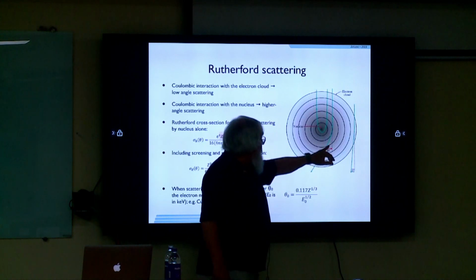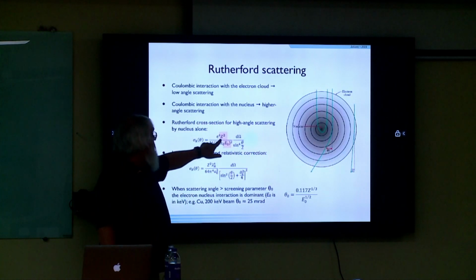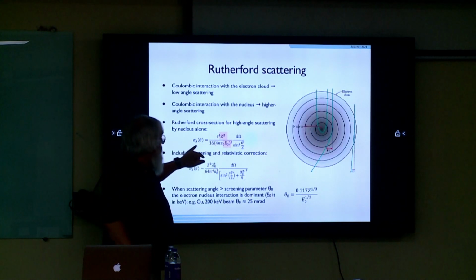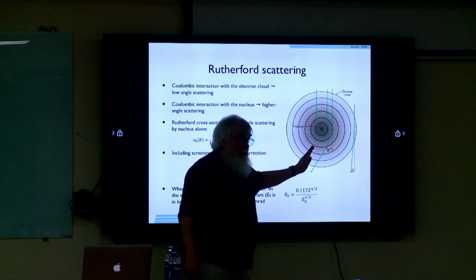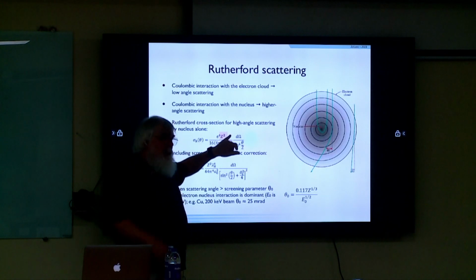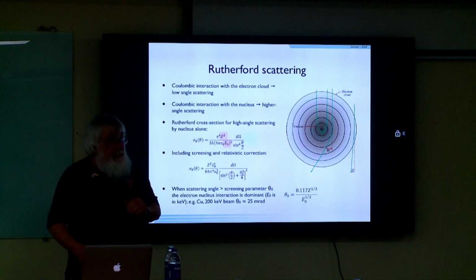We can show that that scattering angle is proportional, roughly, to the atomic number to a power. As long as we're looking at angular scattering, the contrast that we're going to get is inversely proportional to the energy and directly proportional to the atomic number. The models say it's approximately Z squared. It's not always 2, but it's a power law dependence.